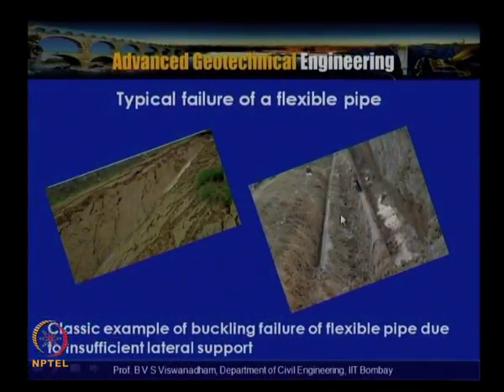The typical failure which happened at the site is shown here. This particular pipe, after excavation, is found like this. Because of the onset of rainfall inundation, you can see that the pipe has undergone a buckling failure, a 3.8 meter diameter pipe which has undergone distress. So these issues of loading on buried conduits are very severe, particularly for flexible pipes with flexibility ratios D by T of the order of 200. Adequate care has to be taken in the design by taking appropriate loading considerations.